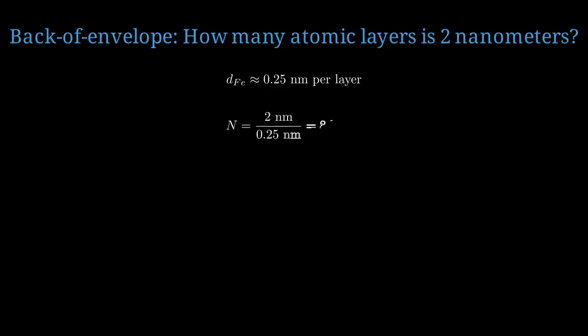Let's do a quick back-of-the-envelope calculation. How many atomic layers correspond to 2 nanometers of iron? The lattice constant of iron is about 0.25 nanometers, so one atomic layer is about 2.5 angstroms. Therefore, 2 nanometers corresponds to about 8 atomic layers. This shows we're working at truly atomic scales, where quantum effects dominate.